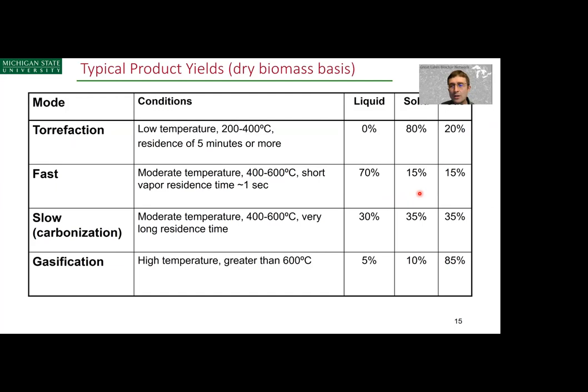Fast pyrolysis biochar yields are about 15 weight% or so. Slow pyrolysis biochar yields are about 35 weight% or so. Yes, you can derive biochar from gasification on the order of 10%, but we just have to be a little careful as to what sorts of organic contaminants that biochar might contain because of the high reaction temperatures we expose that solid material to.